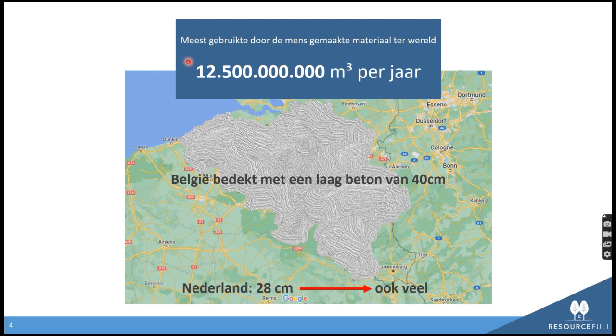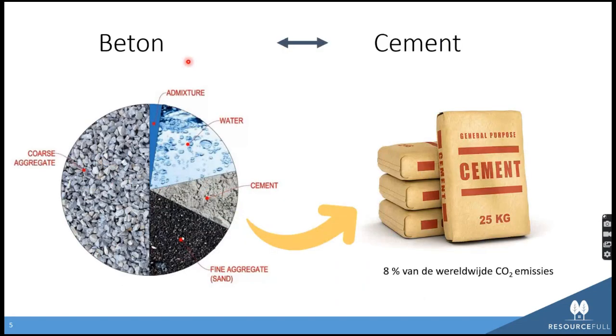So that's an enormous volume of material that we are using. And that's also immediately the explanation why it has such a high footprint, because ton per ton, concrete is by far one of the best building materials to use, but it's a bit the victim of its own success. We make concrete by mixing cement and water, gluing together the sand and the stones, and this 15% weight of cement is responsible for plus minus 90% of the footprint of unreinforced concrete.